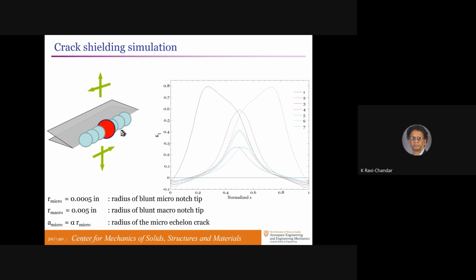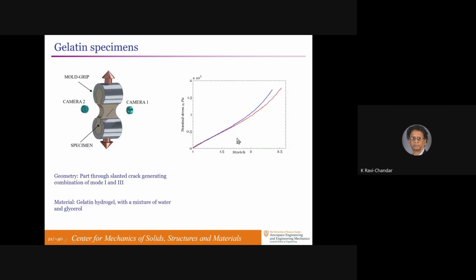If one takes a burst and moves forward, that stress intensity is shown by the red line, it increases. The two nearest neighbors decrease their stress intensity factors because they're shielded. The next nearest neighbor, this one and that one, don't see any effect of that. They don't get shielded. So there's a clear period doubling kind of instability here. If by any accident one of the cracks pops, it will shield the nearest neighbors. The next nearest neighbor can grow. Take that to its conclusion, it'll always period double, and every second crack will stop, and that's what's going on here. Fairly easy to understand.